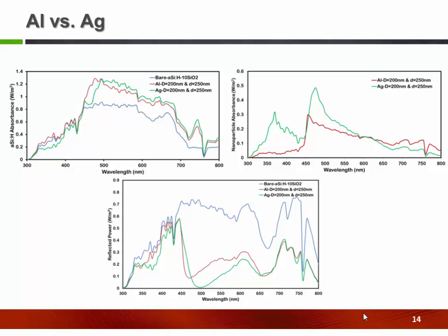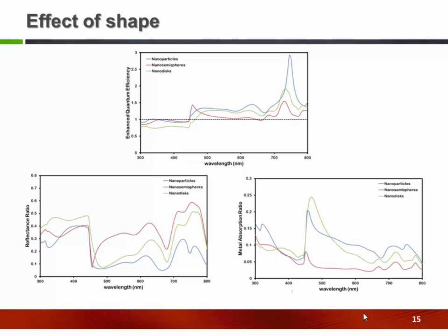So these parameters should be considered for the type of devices that you are going to use for the application that you want to specify for the future. The other parameter is the shape of the devices. I have investigated nanoparticle or sphere, semi-sphere, and nanodisk or disk shape. The most important point that I would like to highlight is that almost all of them show some sort of enhancement, although the sphere nanoparticle has the best performance with respect to absorption enhancement.